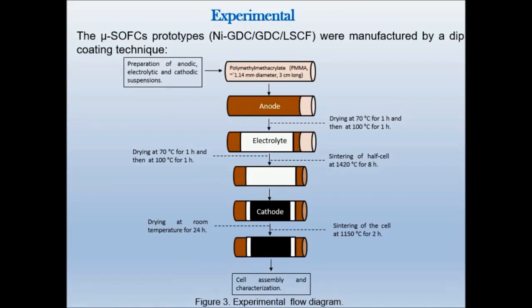Here's how our prototypes were fabricated based on a dip coating technique. Electrolytic and electrodic suspensions were prepared from commercial ceramic powders. Polymethyl methacrylate cylindrical rods were used as sacrificial cores. They were dip coated with the anodic suspension, drying alternately at 100 Celsius for 1 hour until a thickness of half millimeter was reached. Then an electrolyte layer was applied by dip coating. After drying, sintering at 1420 Celsius for 8 hours was performed.